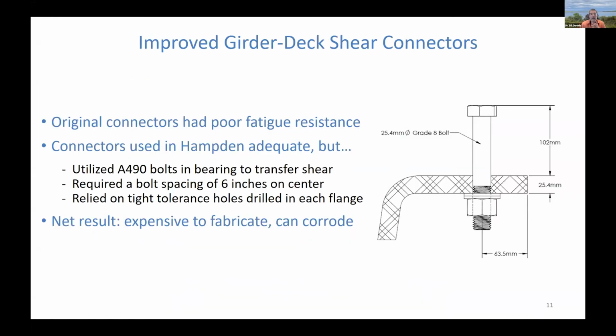Now, another critical issue here are those girder-deck shear connectors. And if you recall from the last webinar, the original connectors used in the first pilot girder test, the 40-foot specimen, had poor fatigue resistance, so we had to redesign them and come up with new connectors to use in the Hampden grist mill bridge. And those are shown in the figure on the right. They used A490 bolts. They were in direct bearing with the girder flange, and they transferred shear directly. They required a bolt spacing of 6 inches on center.